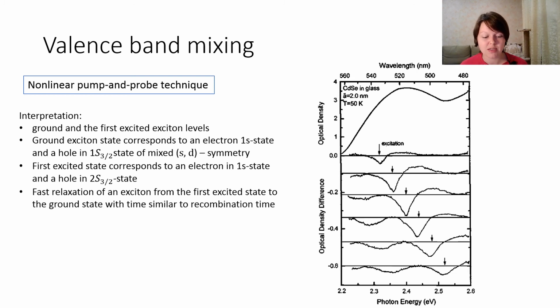First, by means of nonlinear pump and probe spectroscopy. Second, on the basis of the second derivative analysis of the absorption spectrum. And third, and the most obvious one, by using highly monodisperse ensemble of perfect nanocrystals.